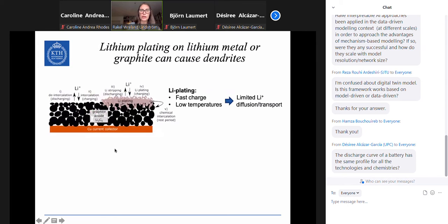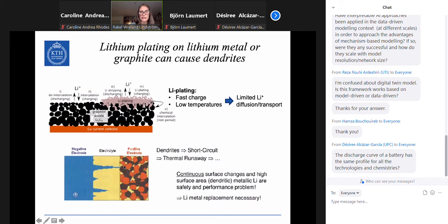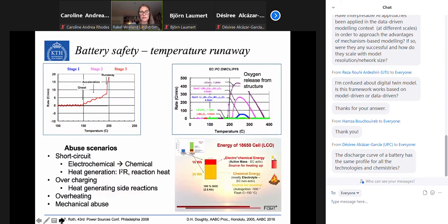Something that is much talked about nowadays is also lithium plating. If the diffusion is slow, then instead of reaction, we can start to plate lithium. And if that is happening, then we can form dendrites like this and we can have a short circuit. And that could then lead to explosion. What can happen is that we produce heat, and when the heat is produced, the organic solvents start to react, and we can have a runaway, and we have these accidents that we have heard about. We actually have very much energy in the material, in the solvents that can burn.